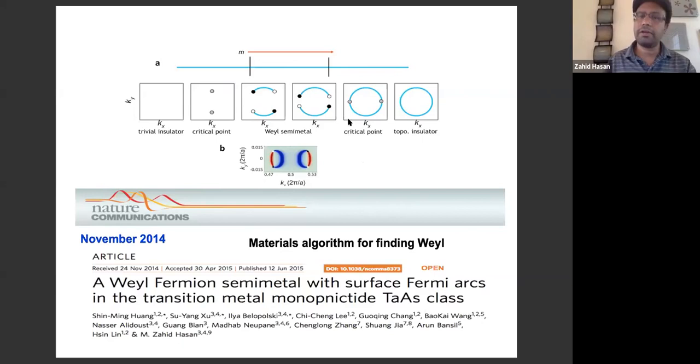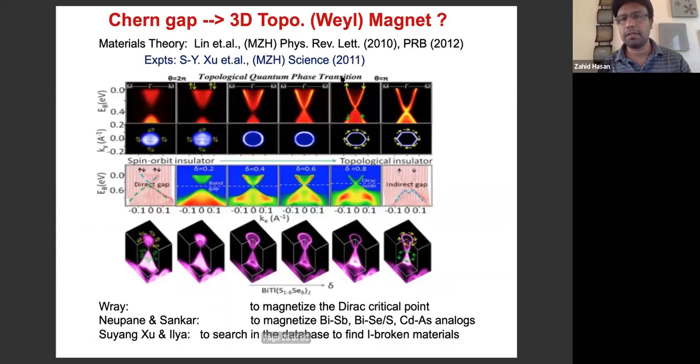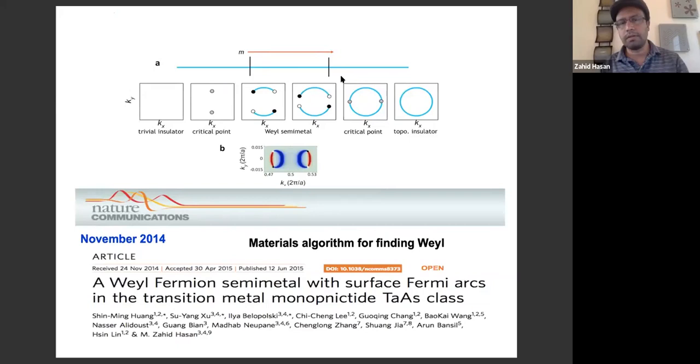Later on, I realized, and this is not in the paper, that in ARPES we never measure the true bulk. We may be measuring the bulk band, but projected near the surface, which is never exactly the same. So the reason our arcs always looked stable is that near the surface we were not resolving it. They were split into volume nodes, because the surface terminates and the inversion symmetry is broken at the surface, so even the bulk band would be modified. So that stability was already telling us it's because of the volume splitting, although because of ARPES resolution, we could not resolve it.